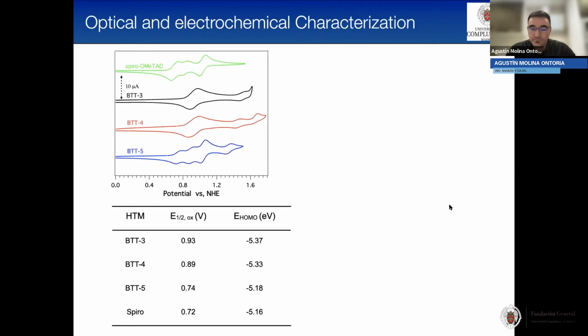Well, as I said before, regarding the position of the sulfur atom, we can have different properties. So from the electrochemical measurements, we can see that BTT5 exhibits 4 oxidation waves. The first one is cathodically shifted, so it is a stronger electron donor, displaying a HOMO energy estimated from solution of -5.18. BTT4, on the other hand, displays just 1 or 2, and this is the central attribute of the central scaffold. We can see this first oxidation wave is not only one, it is a simultaneous process of 3 oxidation processes, and the HOMO energy level was estimated to be -5.33, which was very close to that of the BTT3.